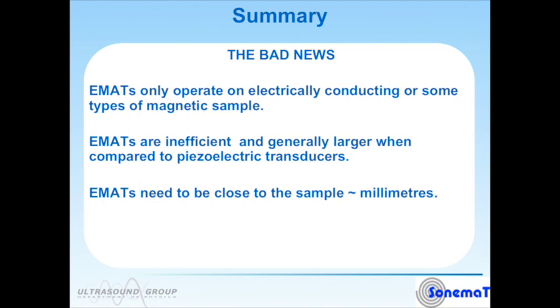EMATs are undeniably inefficient compared with piezoelectric transducers. They also tend to be a little bit larger than piezoelectric transducers. EMATs need to be close to the sample that's being inspected, typically within 5 mm, but the exact distance depends on the kind of EMAT that's being used and the kind of sample that's being inspected. For example, in some situations it's difficult to get significant signal to noise if the sample has poor electrical conductivity, even with the EMAT in direct contact with the sample. In other cases, such as in some of the high temperature oxide coated pipes, EMAT measurements can be taken at distances of over 12 to 13 mm away from the surface of the pipe.